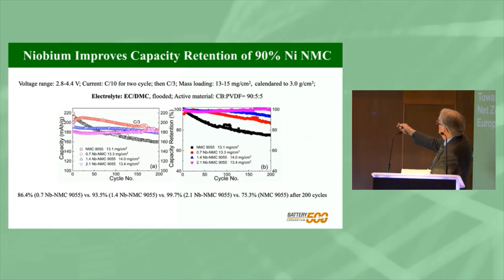And I just show you the same data here as a percentage. So you can see with this purple one, there's essentially no loss in capacity at all for this 200 cycles. So it totally stabilizes the lattice. So it's doing very positive things. We don't like the idea that it's dropping the overall capacity. And I should point out this is now with 90% nickel. So we're trying to push the nickel content as high as we can. And we're staying in a reasonable potential limits for the stability of the electrolyte.